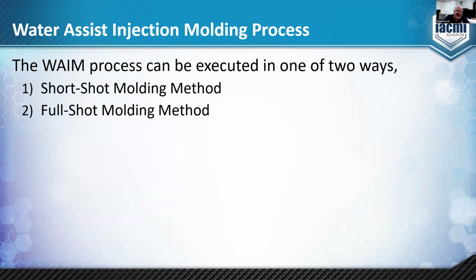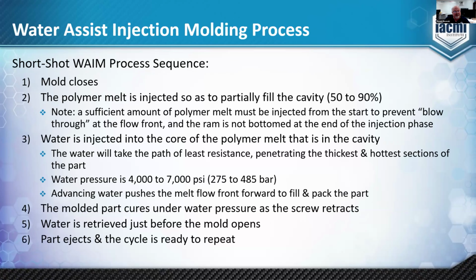So the water assist system, again, can be done in two types of methods, the short shot or the full shot. And I'll give you a little more detail on each of those processes. In the short shot process sequence, the mold will close. The polymer melt is injected so as to partially fill the cavity to 50 or 90%.